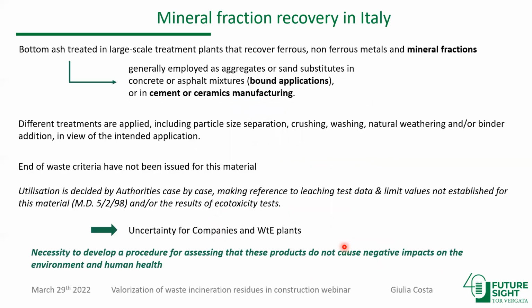Now, looking at the situation in Italy, as I said, bottom ash is being increasingly treated in large-scale plants to recover primarily metals, but also the mineral fractions that are of different particle size ranges and can be used as aggregates or sand substitutes but only generally in bound applications, or if not, in cement or ceramics manufacturing. Different treatments are applied to the mineral fractions at these plants, ranging from size separation to crushing, in some cases, washing. Generally, natural weathering is applied in heaps. And in one of the cases we analyzed, cement is added as a binder.